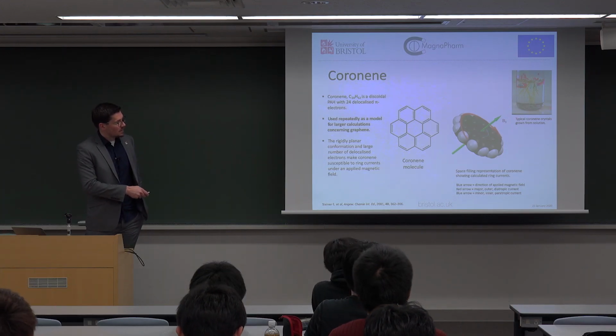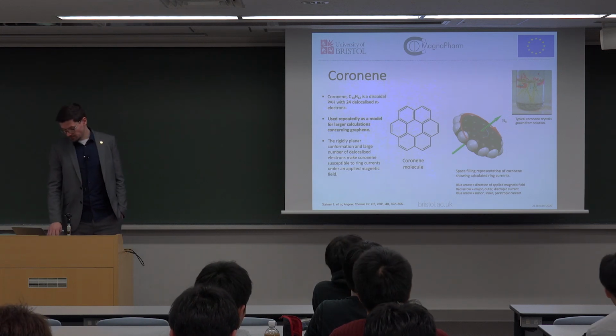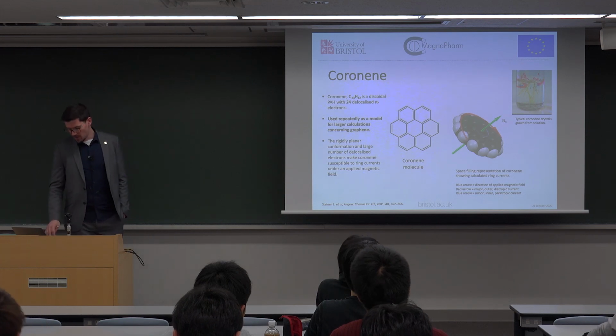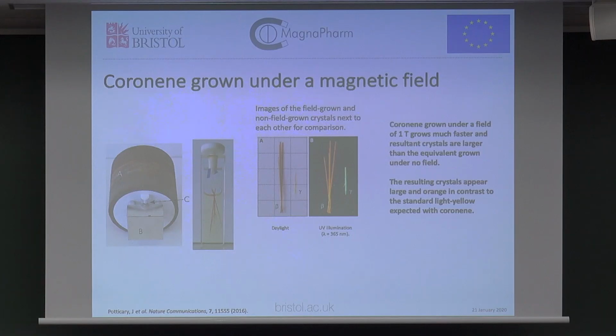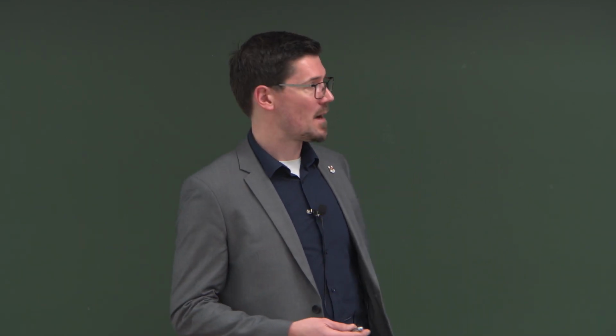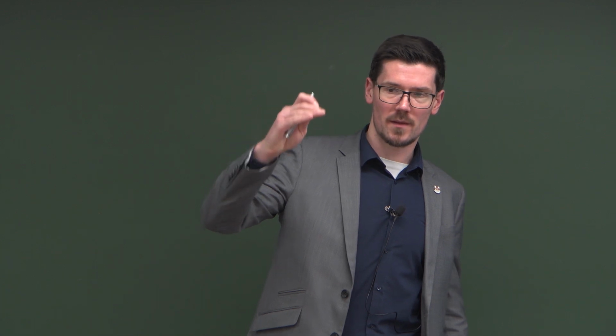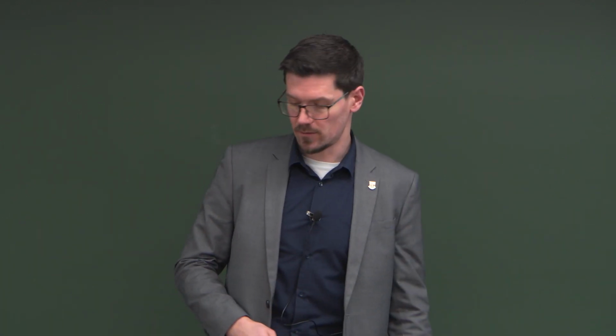Typically, coronene grows in these yellow crystals that are up in the top right-hand corner. So I thought I'd grow them in a magnetic field, and when I perfected the method, I started getting these very large orange crystals. You can see here in the cuvette. It's a very crude setup. Originally, we didn't have these big electromagnets. The big brown cylinder is a pole piece from an old vibrating sample magnetometer, VSM, and this is just a neodymium magnet, and they were just being held together by magnetic forces, and the crystal was grown in there. We put that whole thing in an oven with temperature control, and we lowered the temperature very, very slowly, and we ended up with these big orange crystals.